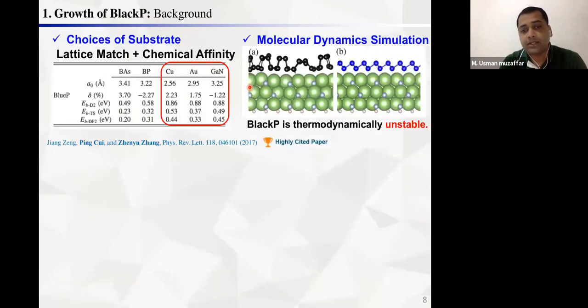Previously, maybe in 2017, in our research group, we considered a number of substrates, which include boron arsenide, boron phosphide, copper, gold and gallium nitride. We tried to identify a good substrate for black phosphorene, but unfortunately none of these substrates is suitable to grow black phosphorene. Our motivation was to identify a good substrate for the growth of black phosphorene, but fortunately or unfortunately, we found that among these substrates,